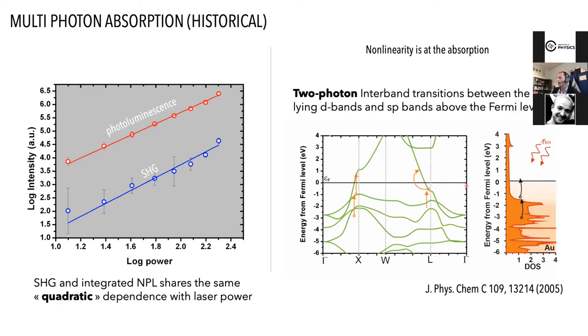And so on the right hand side there, I'm basically plotting a calculation of the local density of states, of the density of states for electrons in a gold structure. You can recognize that this is a Fermi edge, and below the Fermi energy you have lots of electrons here in the d bands, and then you have this empty space here, which are the sp band of the band structure.